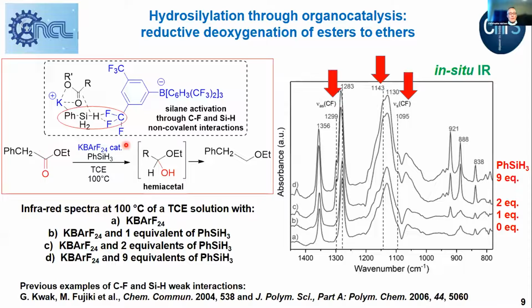This reaction implies the formation of a hemiacetal as intermediate, which allows the further reduction to get the ether. The first evidence of such an organocatalyzed reaction was obtained using in situ infrared. We could evidence these H-bonding interactions between the carbon-fluorine and silicon-hydride bonds by studying this chemical reaction in situ. Just by adding several equivalents of phenylsilane, we could evidence the appearance of these carbon-fluorine stretching bands, which are new by comparison with the spectrum without any reaction. And this clearly evidences such weak, non-coordinating interactions that allow the activation of the silane.